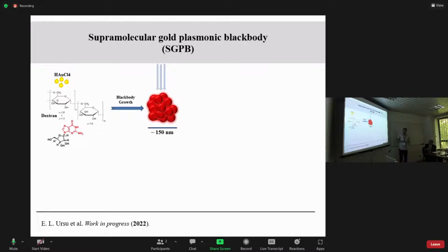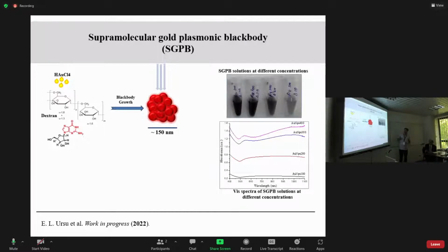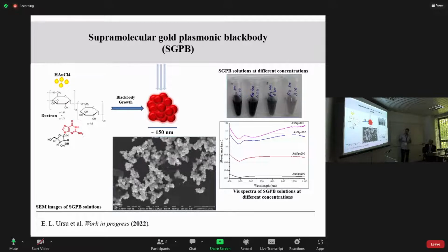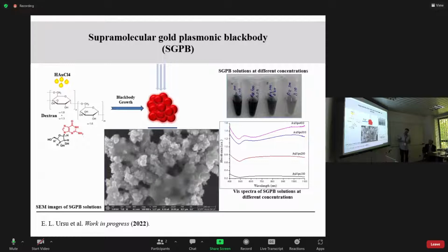Well, this sounds quite interesting because between them all the hotspots are formed, so actually we can perform interesting things with that. It looks like a really black colloidal stable solution. They are stable for quite some time, very interesting. If you see, we performed several dilutions of the stock solution, but all the investigated solutions showed complete absorbance of the visible region of the spectrum. Scanning electron microscopy also confirmed the formation of these clusters, and if you go closer, you can see that these clusters do have small particles bound together in very dense form.